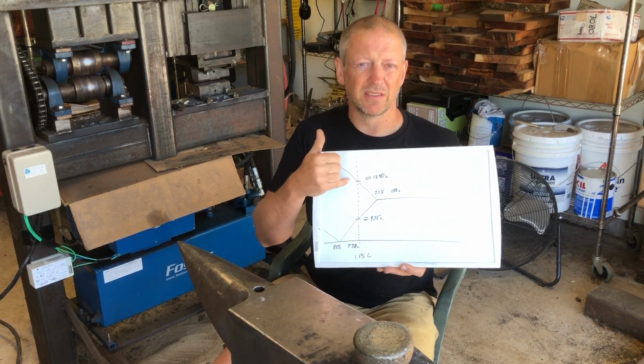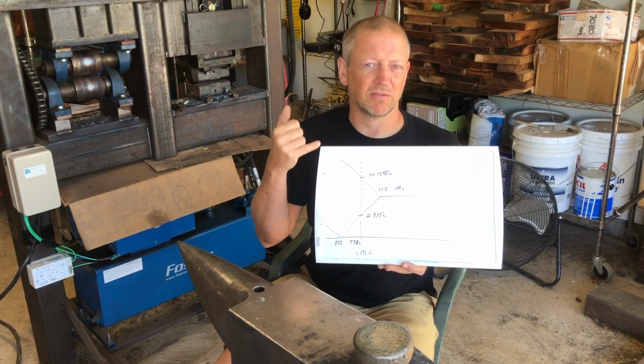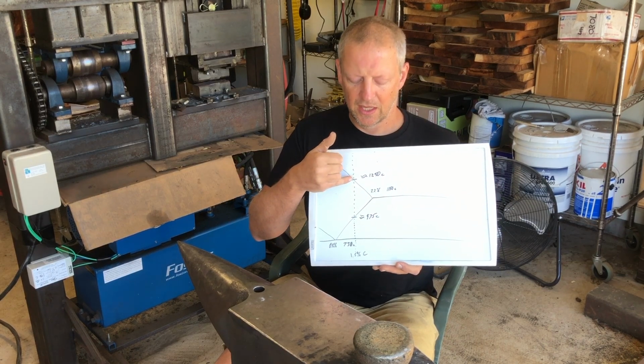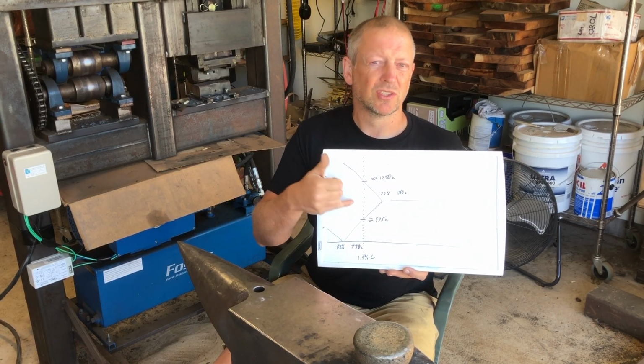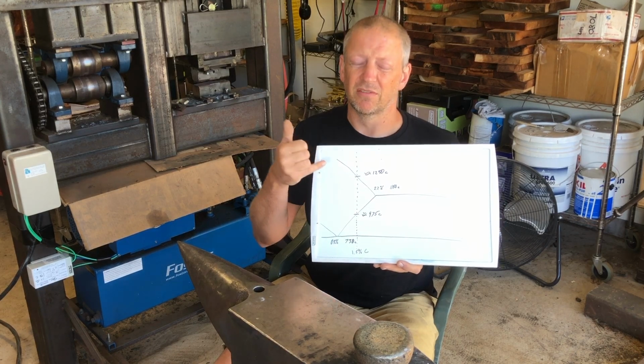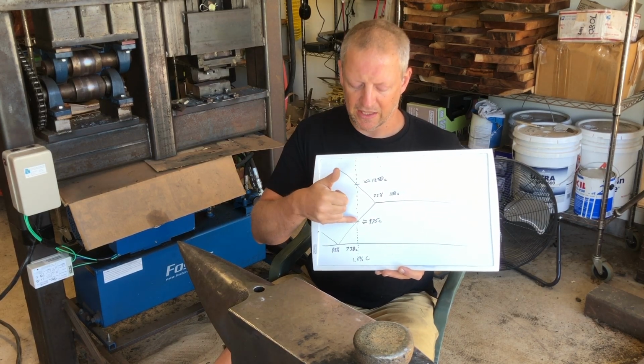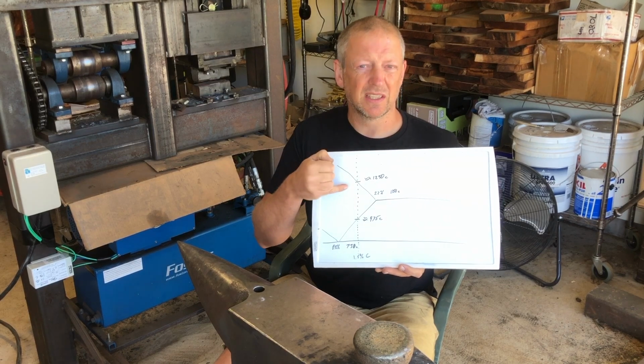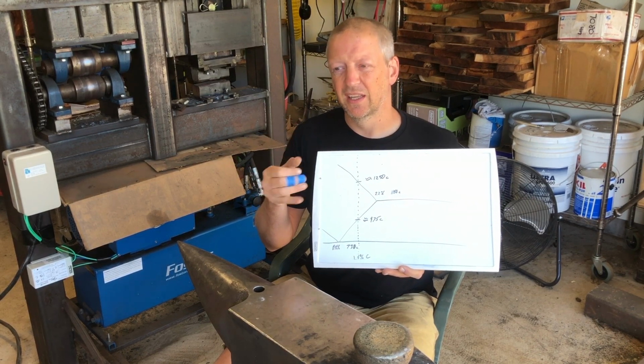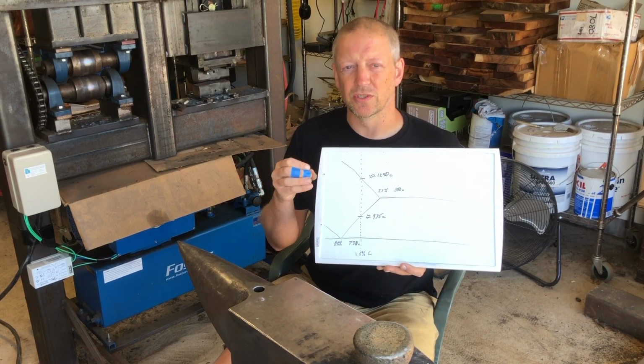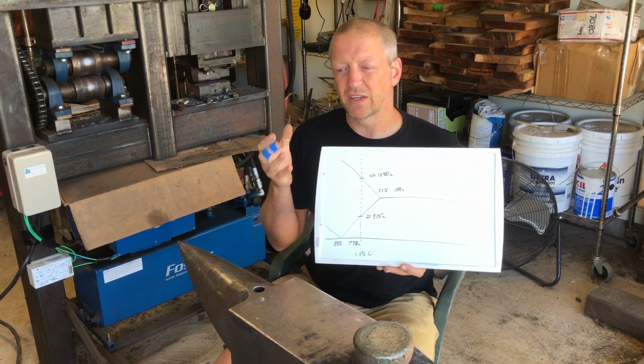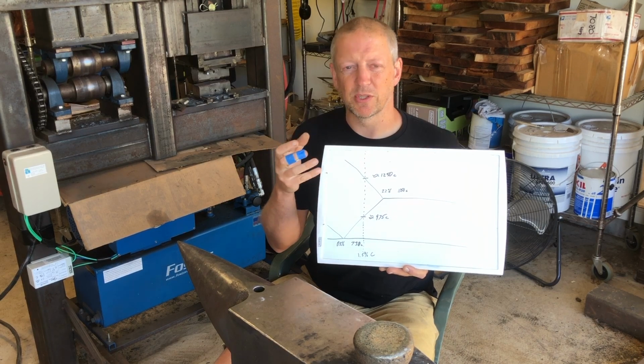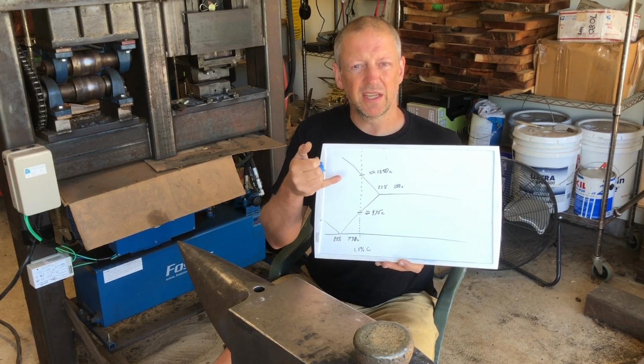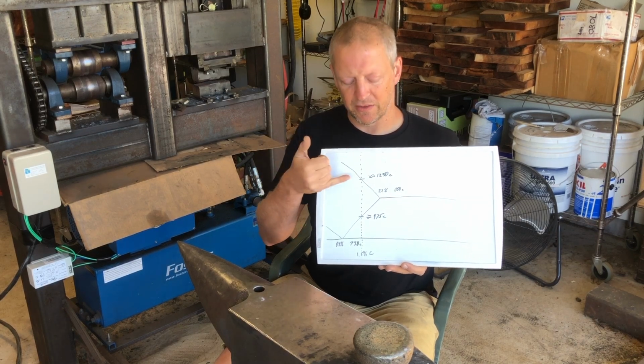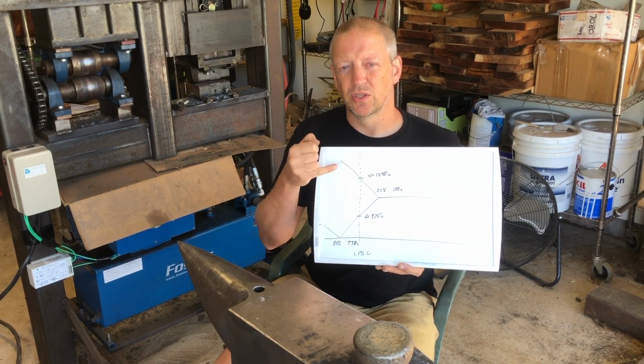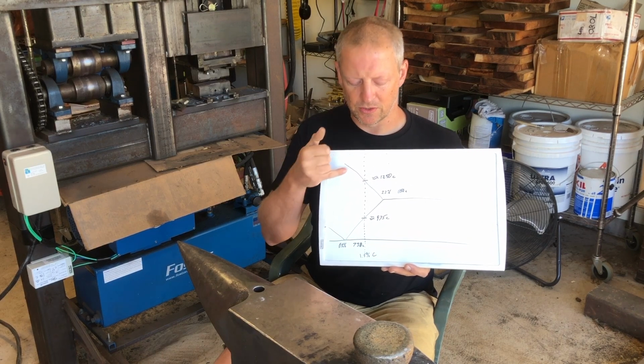At the very top end of this range, carbon is diffusing very quickly. By the time we reach the bottom end of that range, carbon is now diffusing very slowly. And this is why you can have different structures resulting from very similar chemistry in your ingot. It doesn't take a lot of change in chemistry or a lot of change in the cooling rate to greatly affect what type of structure you see.